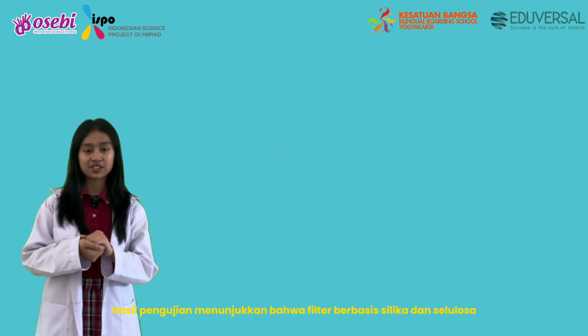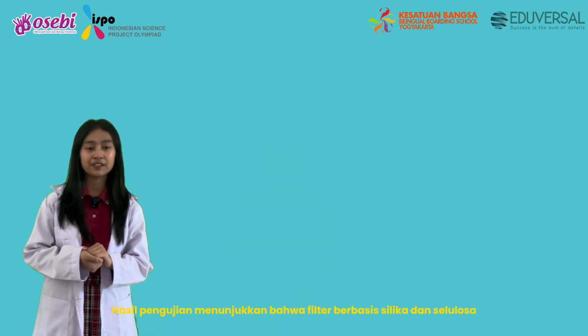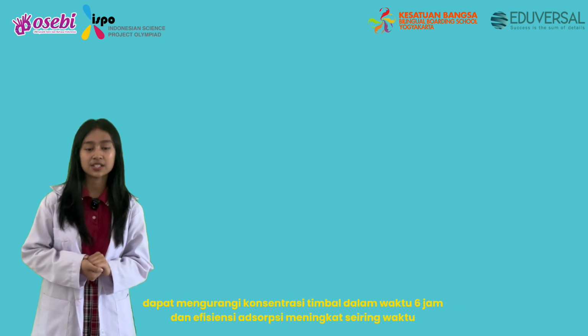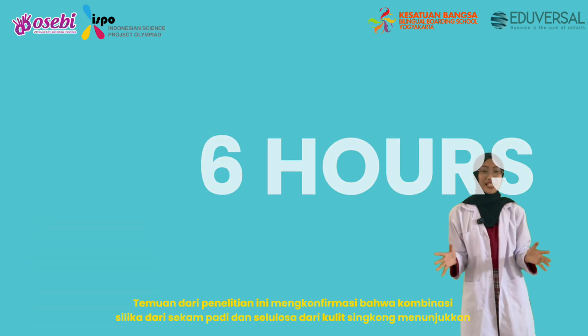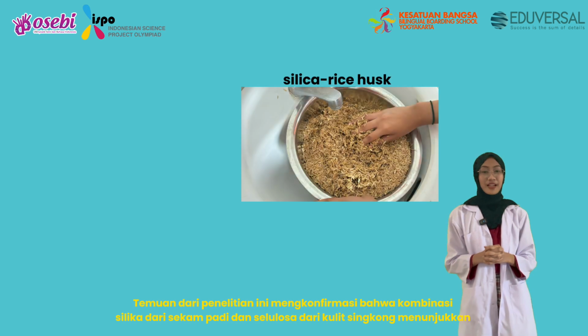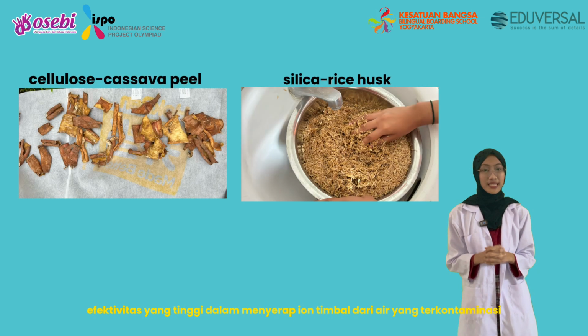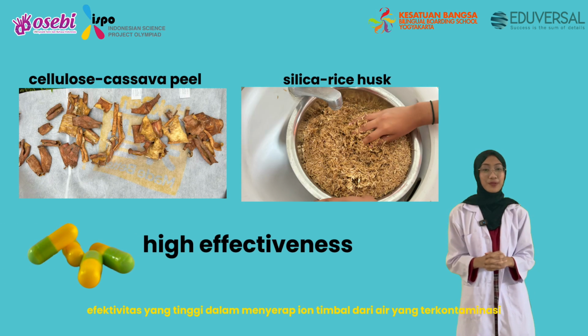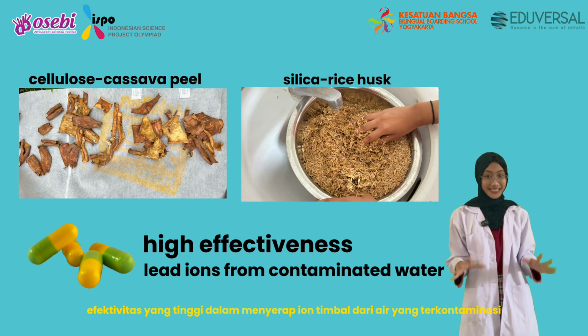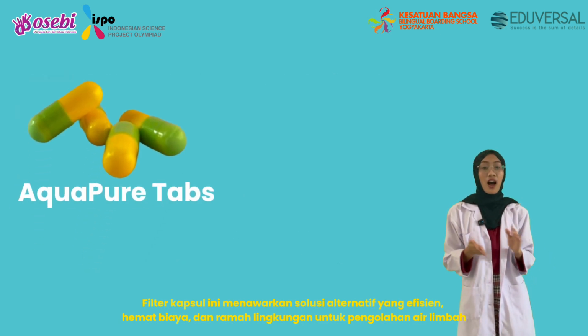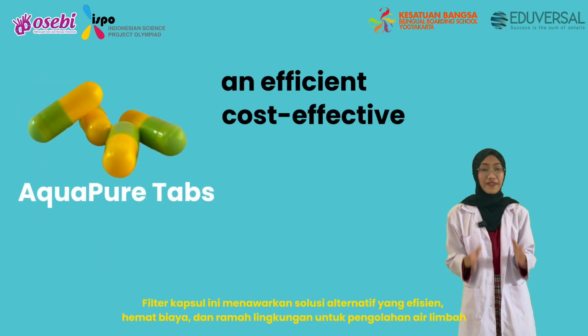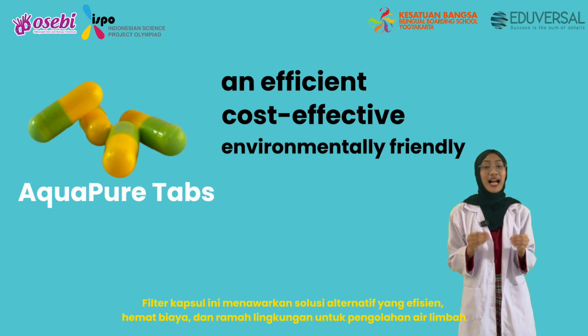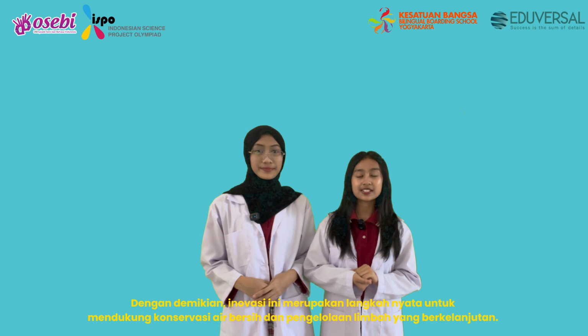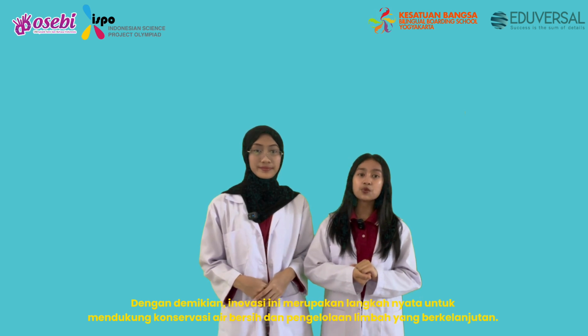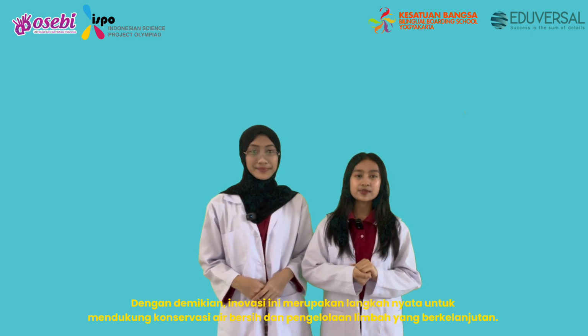The test results demonstrate that the silica and cellulose-based filter can reduce lead concentration within 6 hours. The finding of this study confirmed that the combination of silica from rice husk and cellulose from cassava peel exhibit high effectiveness in absorbing lead ion from contaminated water. This capsule feature offers an efficient, cost-effective, and environmentally friendly alternative solution for wastewater treatment. Thus, this innovation represents a tangible step forward supporting clean water conservation and sustainable waste management.